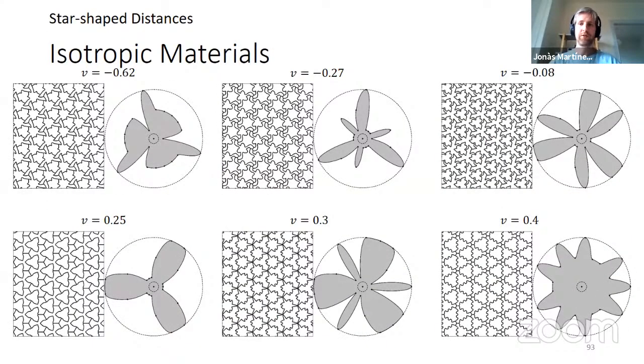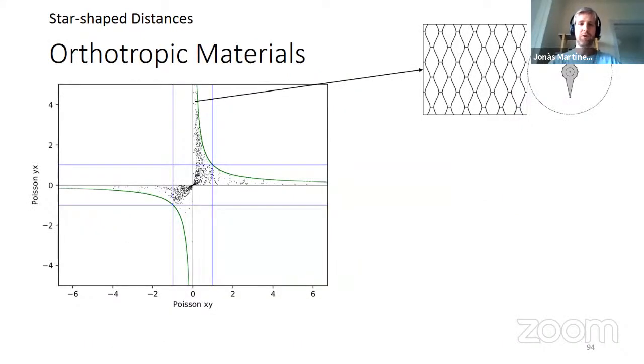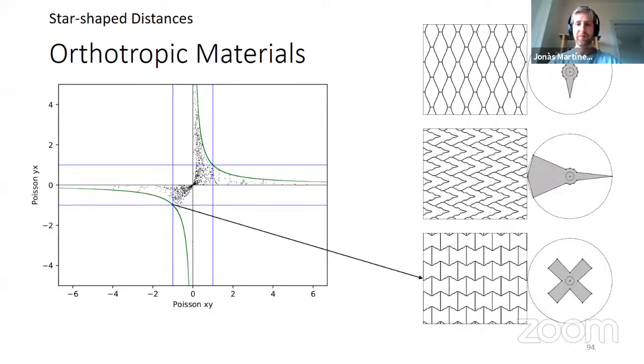So here you have different networks. And as you can see, we can have networks with varying Poisson's ratio going from negative to positive. We can also have different orthotropic materials. So here you can see the green lines are the theoretical bounds. If you get a point outside the green line, something has gone wrong with your simulation. So basically, as you can see, we cover a pretty wide space of ratios. And most interestingly, some combinations lead to pretty well-known networks. So this reentrant cellular structure is something that has been around for quite some time, which means that with our approach, we can transition from well-known tilings to more exotic ones.